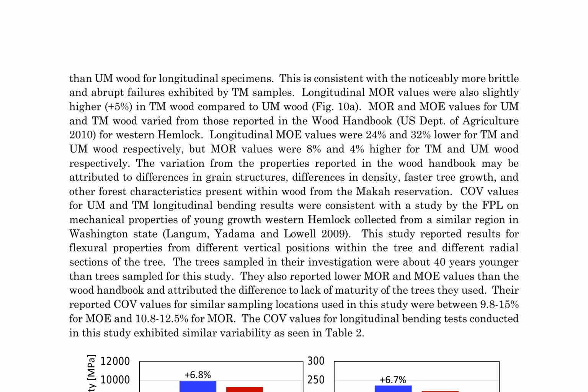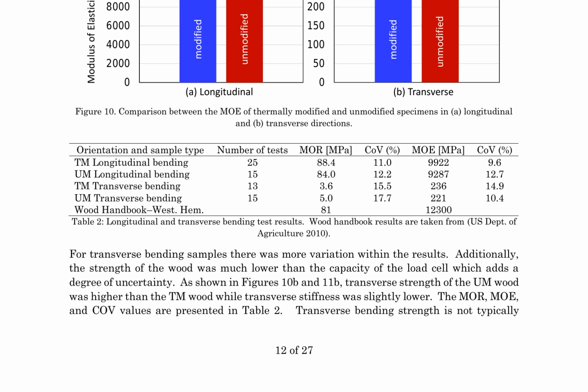The coefficient of variation, COV, values for longitudinal bending tests were consistent with a study on young-growth western hemlock, which reported lower MOR and MOE values due to lack of tree maturity. The study's findings suggest that thermal modification affects the bending properties of wood, particularly in the longitudinal direction. The increased brittleness and reduced deformation of TM wood may be attributed to the thermal treatment process. However, the study also highlights the importance of considering the variability in wood properties, as reflected in the COV values. The results have implications for the use of thermally modified wood in structural applications, where bending properties are critical.